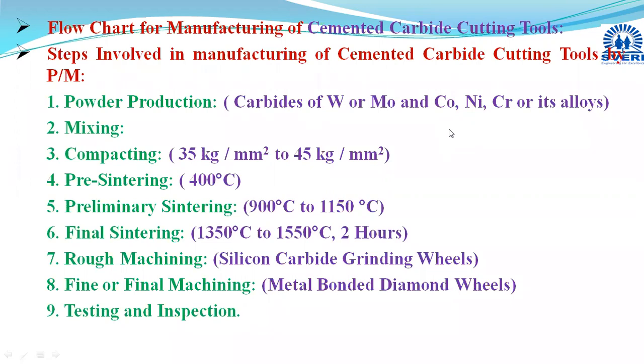Now here these carbides cannot be easily melted because their melting point temperatures are very high, above 1500 or above 2000. They have very high melting points. Now to join them or to create the bond, we are using binders. Here which binder are we going to use? We are going to use cobalt. Cobalt has a melting point in the temperature zone of 1300 to 1500 degrees Celsius. That's why this cobalt material is used as binder to join the carbides. Generally we use carbides of tungsten or carbides of molybdenum for manufacturing of these carbide cutting tools.